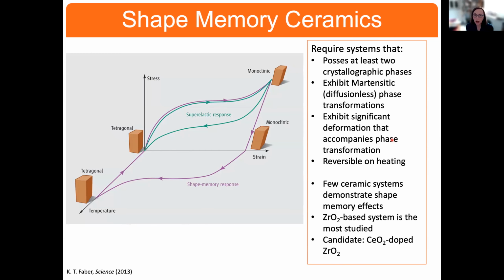So these materials are known as shape memory ceramics, in which they can behave in a way that they undergo a crystallographic phase transformation. And I've shown this here schematically. Here's a stress and a strain curve. And we can start with a material that is tetragonal in terms of its crystallography. And by imposing a stress on the material, we can convert that to monoclinic.